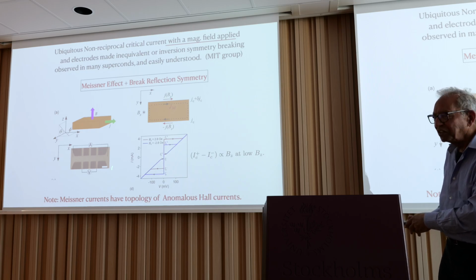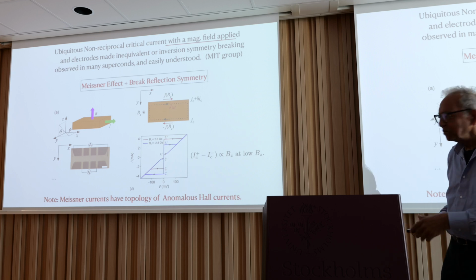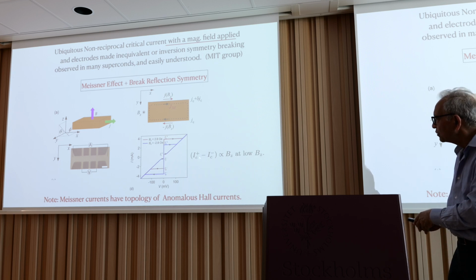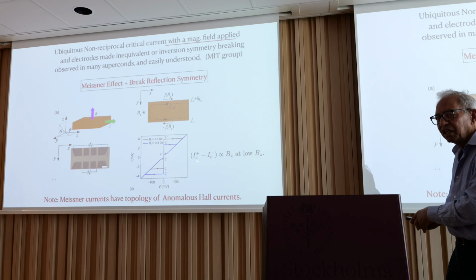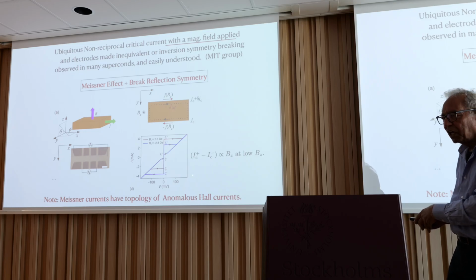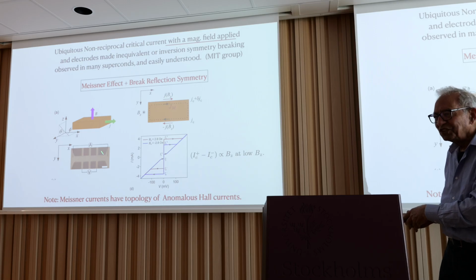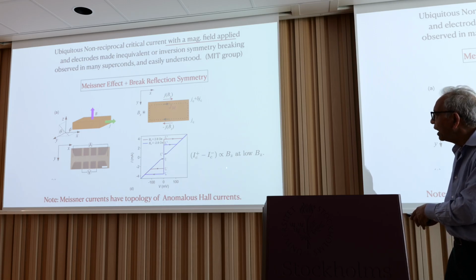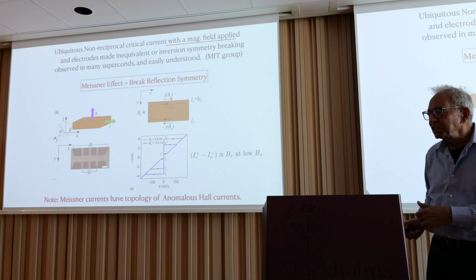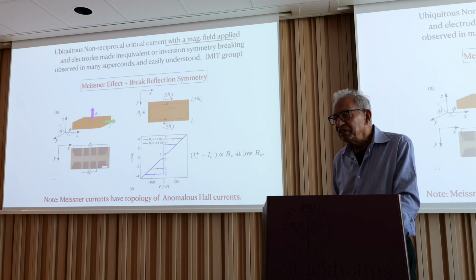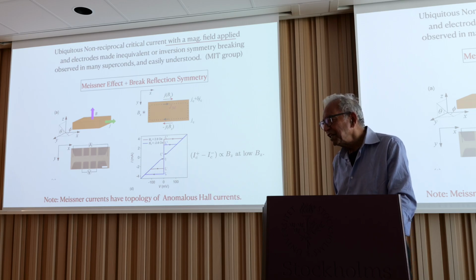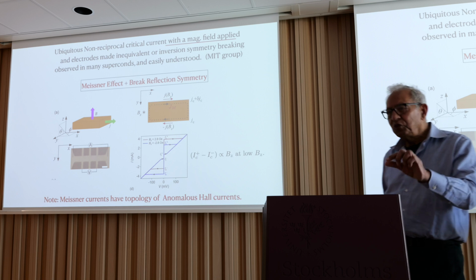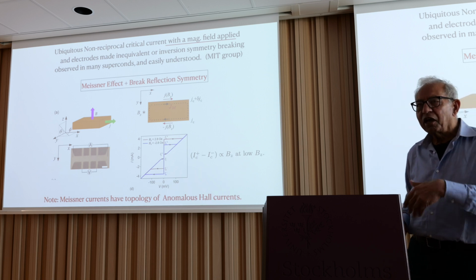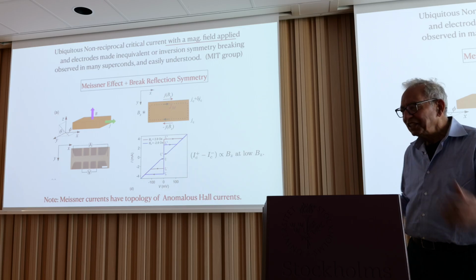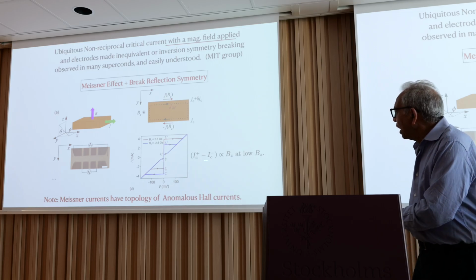Here, current is plotted here and voltage is plotted reversed from the previous one. And you also observe that in these experiments, the difference of the critical current is linear in the applied magnetic field, meaning it changes sign as you change the direction of the field. Whereas in Dr. Wang's experiments in the cuprate, it decreases quadratically with field in both directions if you apply a tiny field. About 0 field, you observe it, and then it decreases quadratically.